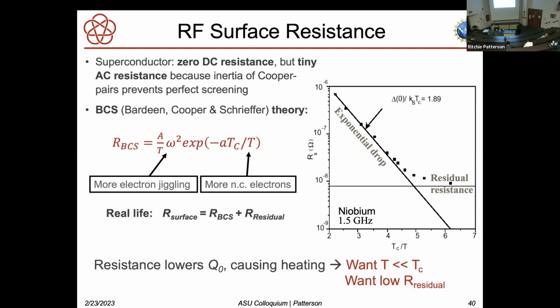It turns out, however, that in the presence of oscillating fields, they do have resistance. And BCS theory tells you that that has a functional form like this. It's proportional to the frequency squared. We're typically operating in the gigahertz regime. And then the resistance also goes down exponentially with temperature relative to the critical temperature of the material. And you can see all that here. We're going to lower temperature to the right. You can see this exponential drop in the resistance. And then finally it bottoms out, and there's some additional resistance coming from other sources that we'll talk about in a second. But the bottom line is that the resistance has two terms, one of which falls exponentially with temperature and the other residual.